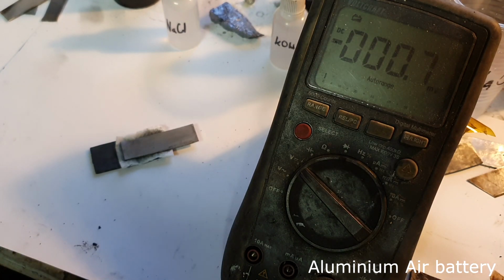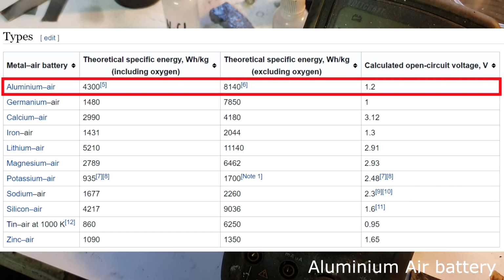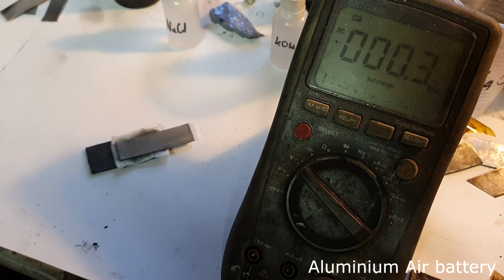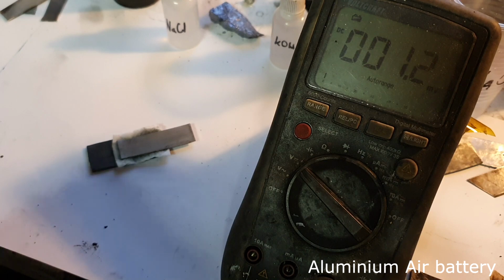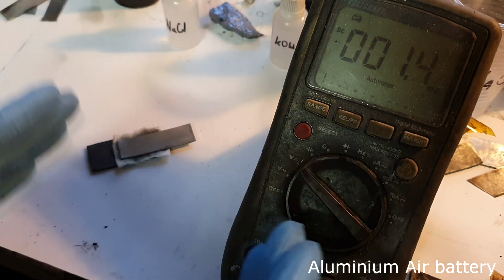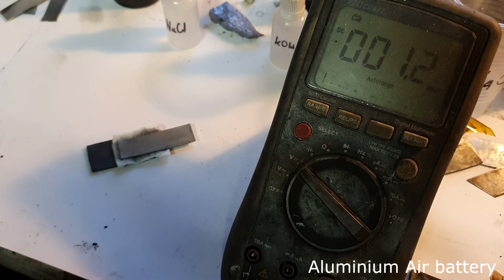According to Wikipedia, if you search for aluminium air battery, you will find that it is described as having a voltage of 1.2 volts. So with this system, I get 1.5 volts and a capacity of over 8.1 kilowatt hours per kilogram. 8,100 watt hours per kilogram. This is a lot. This is really, really a lot. But the capacity of this aluminium air battery, and also of all metal air batteries, depends on the size of the battery and also the surface area of the battery. The larger the surface area, the more capacity you will get. But the size of the battery, whether small or large, will not affect the voltage. The voltage will always be the same.